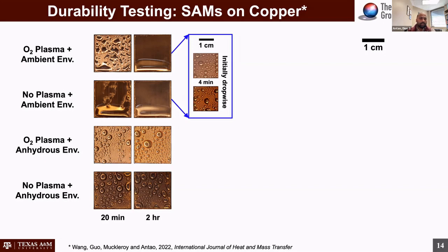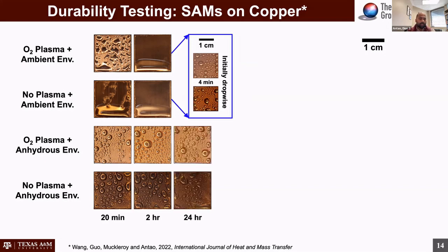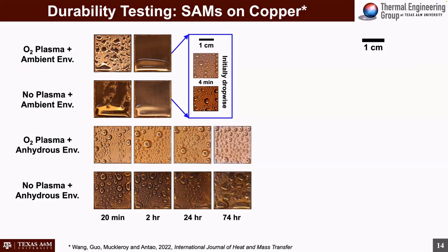And the top row demonstrates exactly what people see in the literature. It starts out at dropwise condensation, and then within 20 minutes to half an hour, it starts to fail. Within 2 hours, it's all gone. And the no plasma ambient environment coating has no chance. Absolutely, it fails even faster than the plasma treated surface. What we did observe was the anhydrous coating environment, even without a plasma, seemed to do fairly well right up to about 24 hours, after which the coating started to fail.